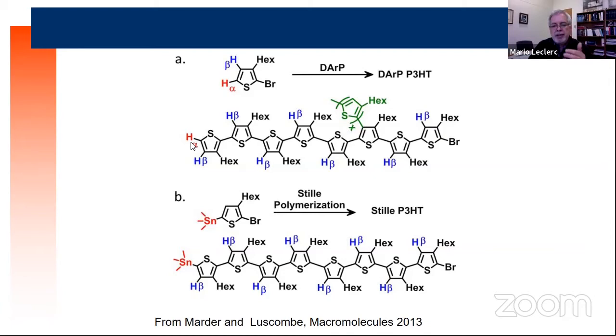So you need a yield close to 100%, a very good ratio or stoichiometry between your reacting units, and a selectivity close to 100. Because with a polymeric chain, you cannot remove the byproducts. If you have beta branching here, it is covalently linked and you cannot remove it. So you have to deal with defects, and you cannot do sublimation or purification. You cannot purify a final copolymer or a final polymer. So the selectivity from the starting point has to be very high.